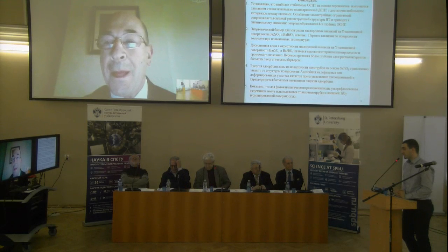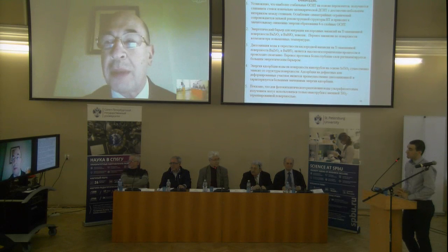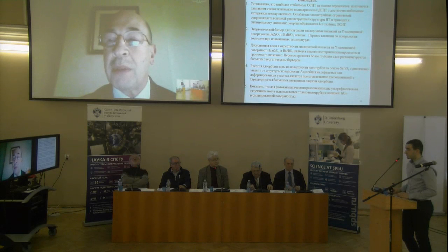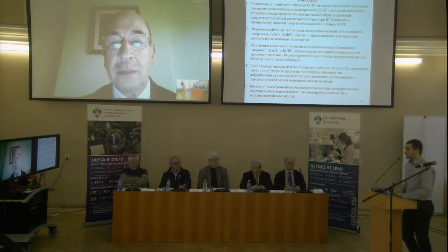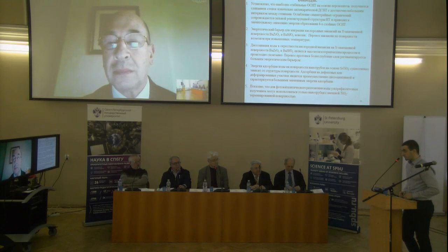Well, actually, the stability criterion was assessed by the energy of formation. The more negative the formation energy of the structures, the more stable these structures were considered. But the formation energy depends on the chemical potential. For example, you can choose the chemical potential of oxygen, and depending on how you choose it, the results will change. So what criteria or parameters were you guided by in choosing the chemical potential? Well, frankly speaking, it's difficult for me to answer this question.